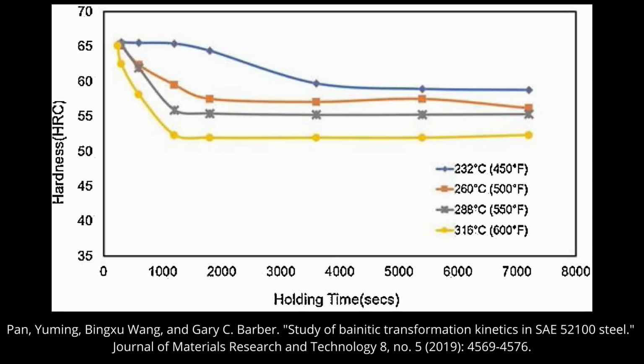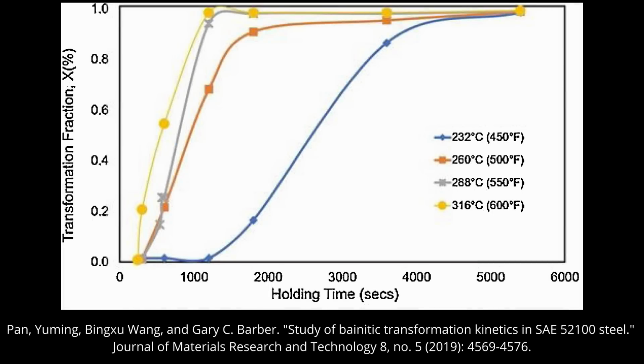Now, to just look at a couple example curves of the transformation, these are the percent transformed at each austempering temperature for different times. And you can see that it forms kind of an S shape where it takes a little bit for the transformation to start, just like in our TTT diagram. Then it transforms, it kind of ramps up, and then it has kind of a period of linear transformation, and then it starts to slow down as it gets closer to 100% transformed. So if you are making your own transformation, you need to pay attention to any small decreases in hardness because you may be at this top of the S, where only small amounts of bainite are forming at that point.